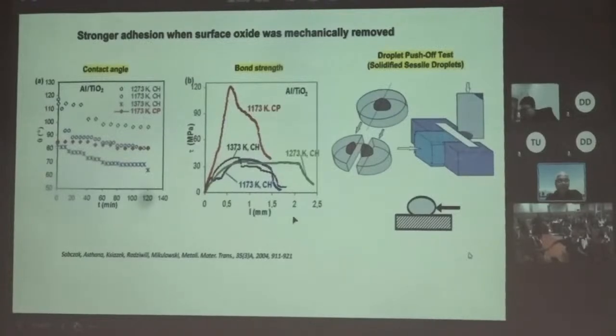And this is just showing you the same thing, but we are looking at the bond strength after measuring the contact angle. So we let the droplet solidify, then we bisect the droplet and do a shear test to measure the shear strength. So what we have seen is that when you remove the oxide on the surface of the droplet, the bond strength really goes up, even at relatively low temperatures, as compared to if you had contact heating.